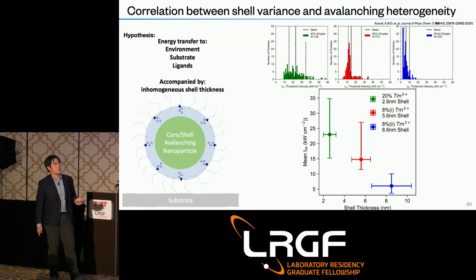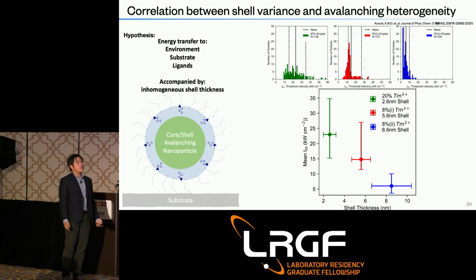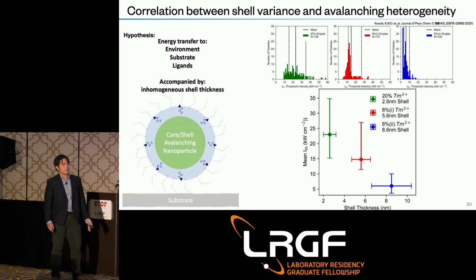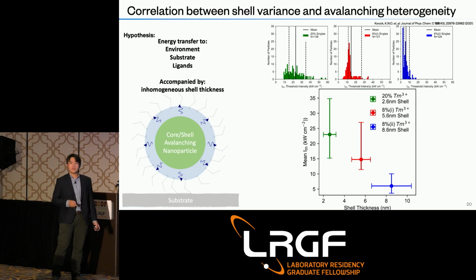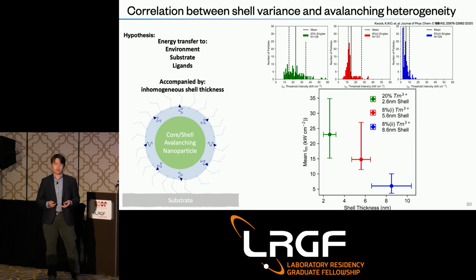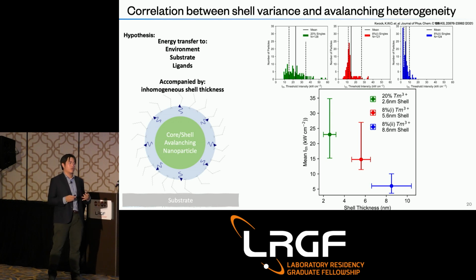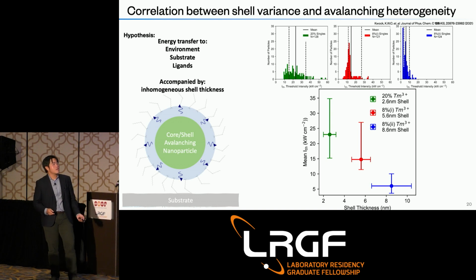Now, when you start to look at the relationship between the three batches, there is a relationship that starts to show up, and this is very much in line with what chemists have seen earlier: when you passivate your nanoparticle with thicker and thicker shells, you tend to get better isolation from environmental effects. Once you're past 6 nanometers, you're really starting to get very good passivation from environmental effects.